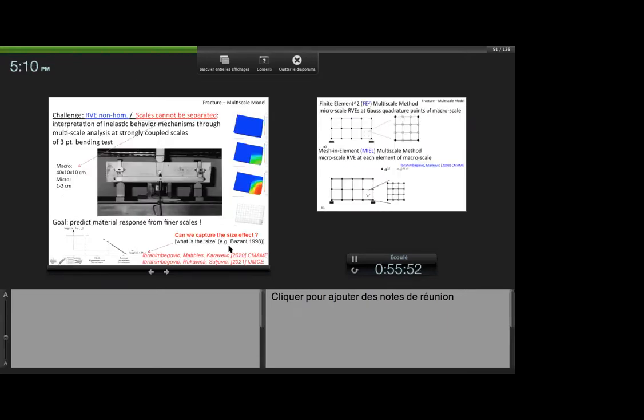The most strong advocate of size effect was Bazant, and frankly, I never understood his point. Typically, in these cohesive materials like concrete, the way you're testing your tension resistance is by 3-point bending test. You cannot put concrete into a testing machine like steel and just pull it vertically. It will be crushed if you put it in the testing machine. So what people do, they use 3-point bending. Here are 2 supports, and here's the force pushed in the middle. So you have lots of tension here, lots of compression there.